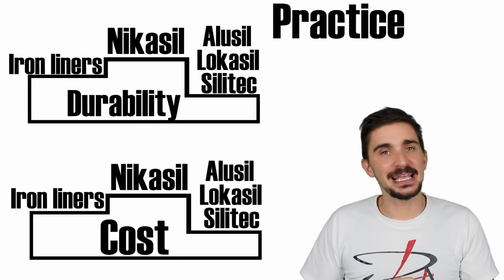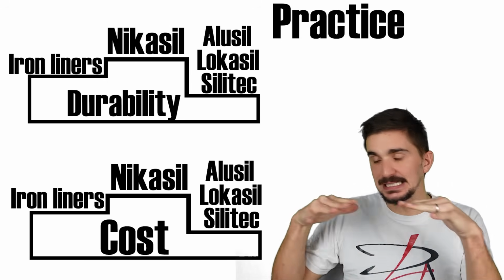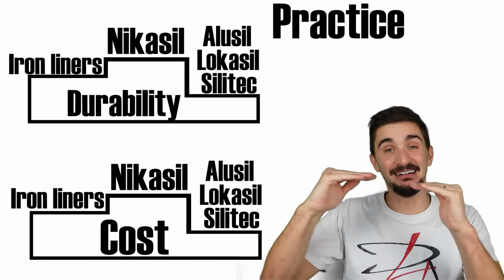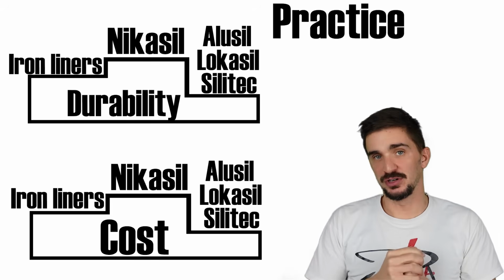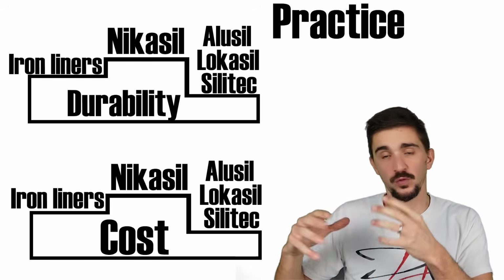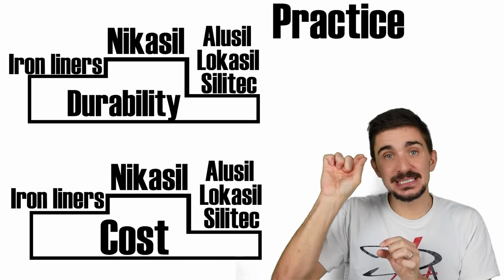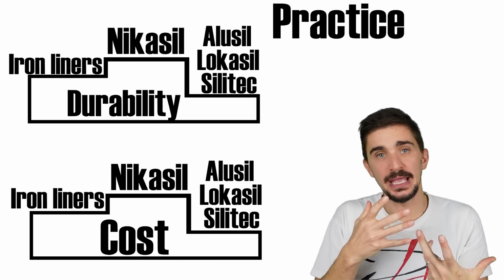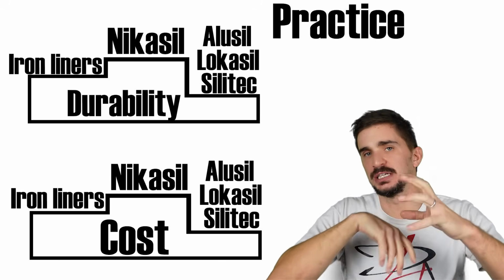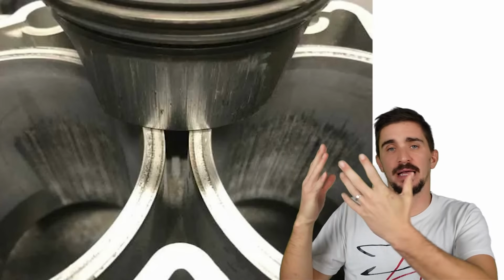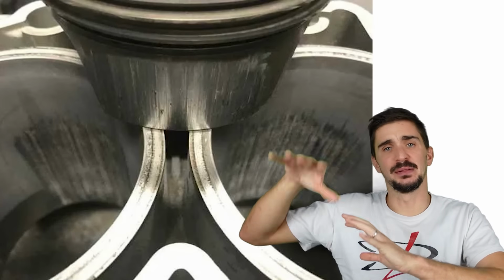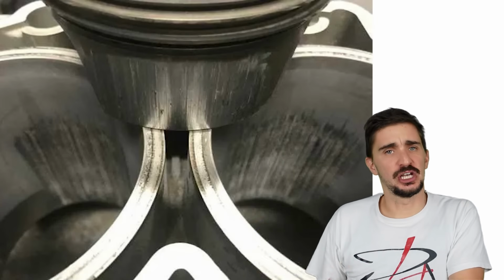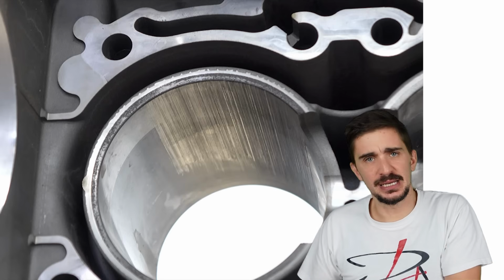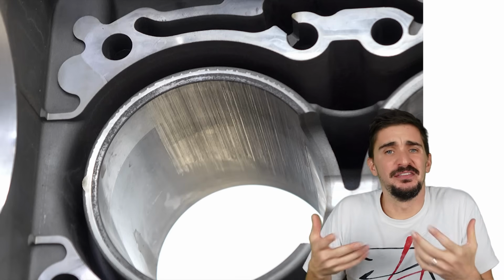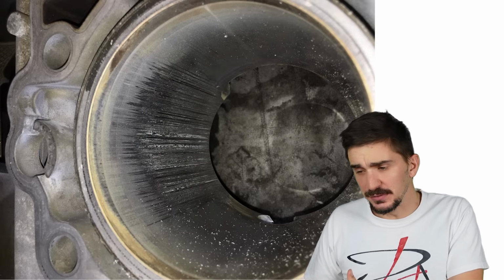Unfortunately, in practice, Lokasil, Alusil, and Silitec proved to be less durable. They lasted less than a traditional cast iron liner. The issue is that over time, the exposed silicon particles broke away. They fell off from the cylinder and circulated through the engine. The bores were left exposed. We got bore scoring, loss of compression, high oil consumption, and eventually a failed engine that needs a rebuild.